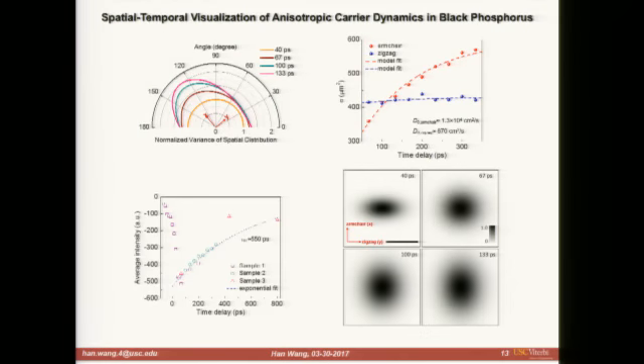So we've been able to extract the diffusivity along the X and Y direction, a factor of 10 to 15 difference. This hot carrier diffusion shows it's more related to the ratio of the effective mass in these two directions. While for near equilibrium transport, like if you measure the mobility, that's heavily influenced by scattering, it's only a factor of 2 difference in these two directions.